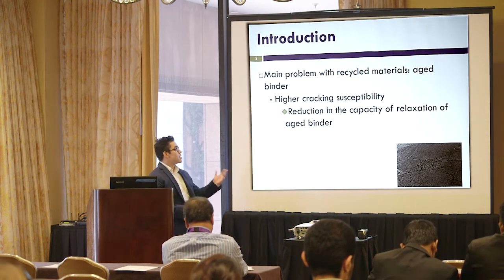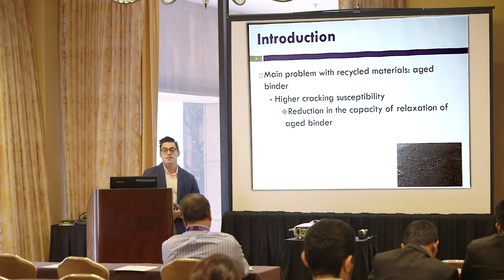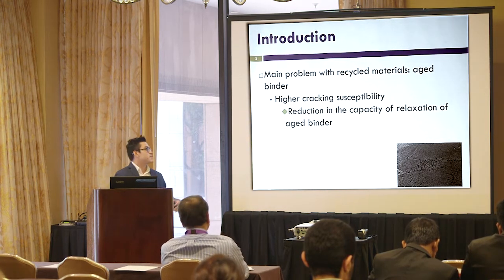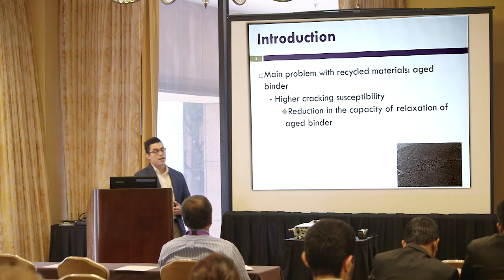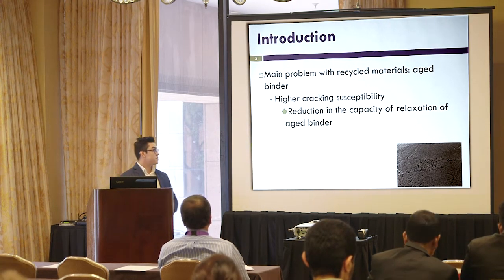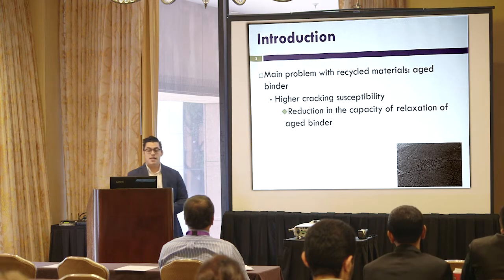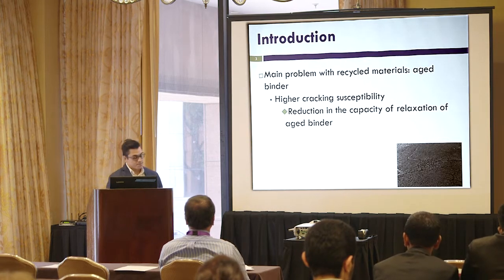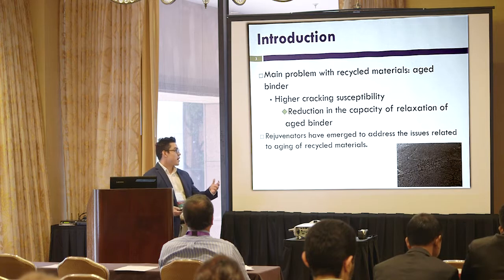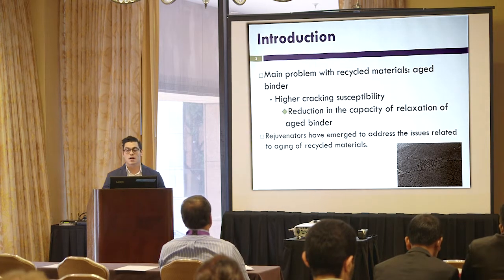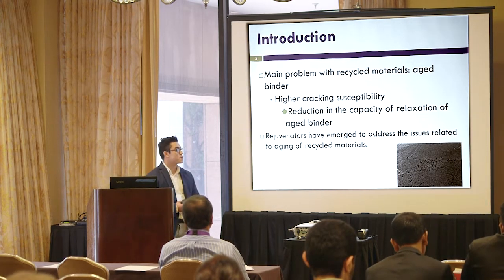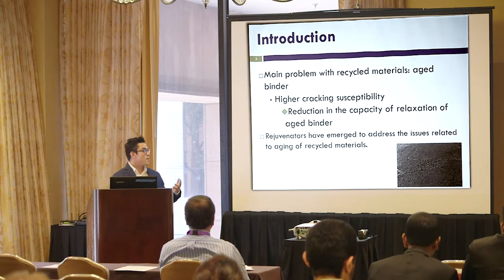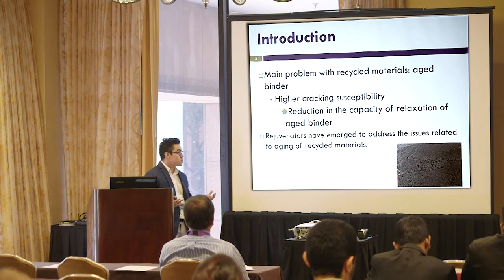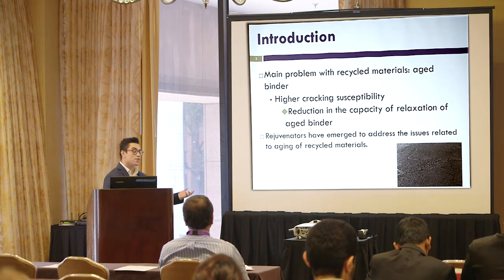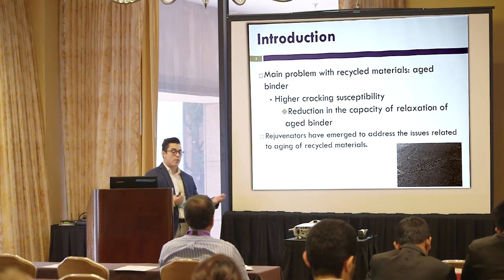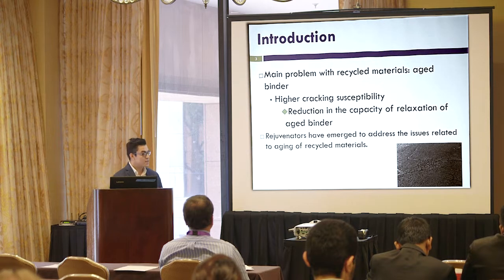However, as we know, the main problem of using this recycled material is the aging factor, which increases the cracking susceptibility of the mixtures because of the reduction in the relaxation capacity of the binder. However, we have found rejuvenator products to address these issues. And using this type of product is not new. We usually use it as a surface treatment or we incorporate them into the mixing process.